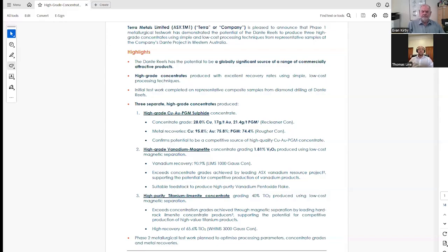I think something from talking with you, Evan, as well over the past few weeks, it's interesting with the vanadium that quite often, irrespective of the head grade of a vanadium deposit, it can be very difficult to increase the vanadium concentrate grade even using magnetic separation above 1.5%. Can you tell us why other companies often struggle to upgrade their vanadium to the higher concentrate grade? Because obviously the higher the V₂O₅ concentrate, the cheaper it is to convert it to pentoxide flake. So it becomes extremely important. That concentrate grade is really the key factor in driving vanadium product economics.